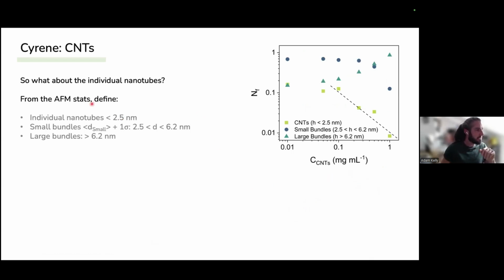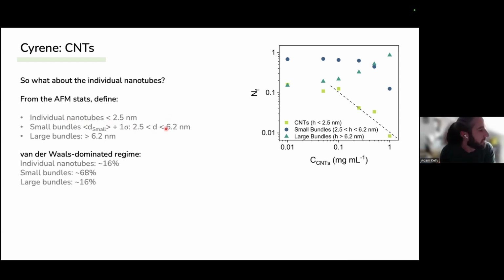So to analyze this a bit further, we go to our AFM stats again, and we define an individual nanotube as anything with a height below 2.5 nanometers. We define a small bundle as something with a height that is the diameter of the small bundle plus one standard deviation, which is 6.2 nanometers. So anything between 2.5 and 6.2 nanometers is a small bundle, and anything larger than 6.2 nanometers is a large bundle. So we find the van der Waals dominated regime, which is below 0.1 mg per mL. We get individual nanotubes at a yield of about 16%, which is about the same as that of large bundles. And then down here in this regime, we are dominated by small bundles with about 68%.